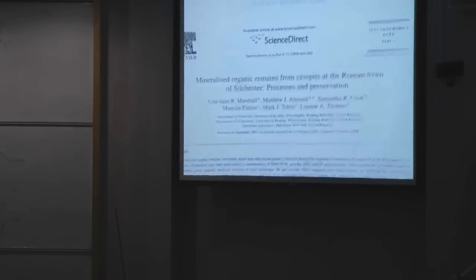The interesting thing about the carbonate peak is it's split into two, and the splitting occurs because the carbonate is located in a matrix of phosphate. So it's in a particular environment where the asymmetric stretch, which is degenerate, splits into a doublet. And by looking at that splitting, you can tell something about the mineral phase that you're looking at. We found that this was a mineral phase called dahllite, which is a mixed phosphate carbonate type of phase.